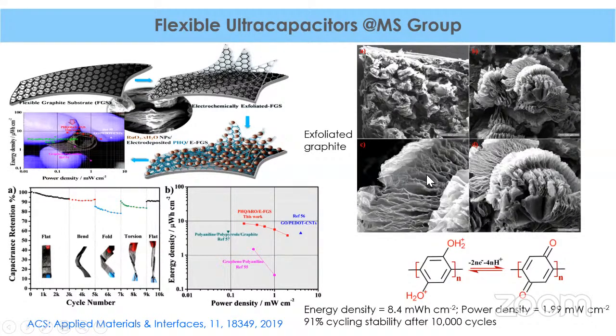So each ordered 2D graphene layer is interconnected to the bulk of the substrate. So that also facilitates maximum electronic conductivity. And then he has coated them with ruthenium oxide nanoparticles using the sol-gel technique. And on that assembly, he coated this polymer molecule. This is polyhydroquinone. Okay, so he electropolymerized it using a monomer of hydroquinone.